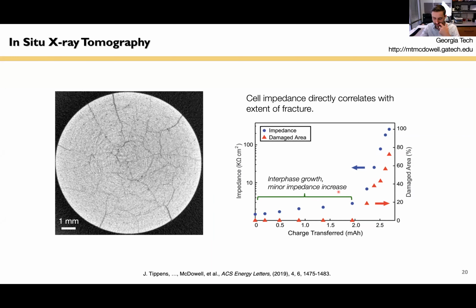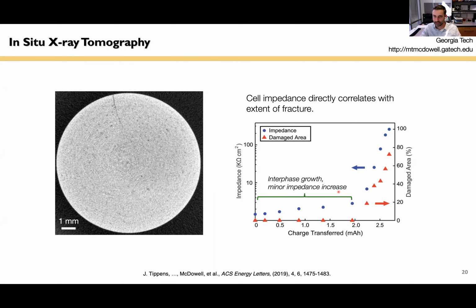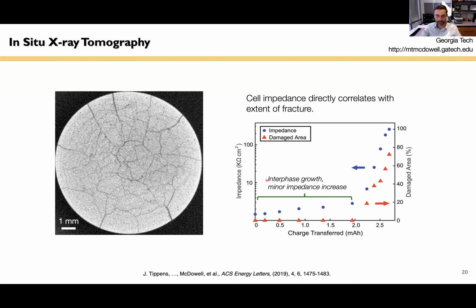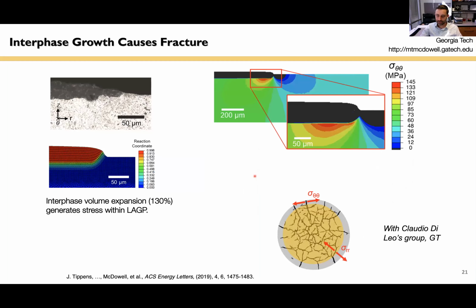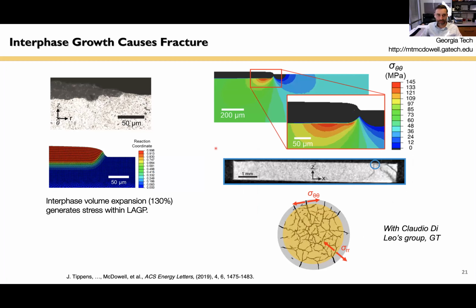And this is a little bit different than what's been assumed in some other studies, which is why we were excited about this. So with that being said, we worked with Claudio Di Leo's group at Georgia Tech to do some mechanical modeling of interphase formation. And it turns out that all these cracks in the fracture process here is basically caused by interphase formation. So we're looking here at a half of the cross section of one of these pellets. This is a finite element model. And the interphase is this black region up here. It's this expanded region. It's an amorphization expansion process.